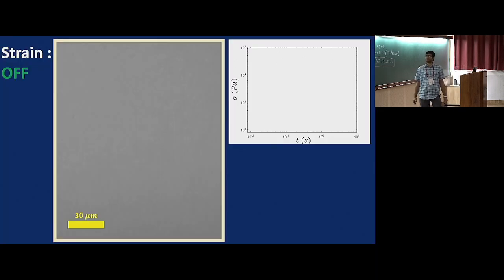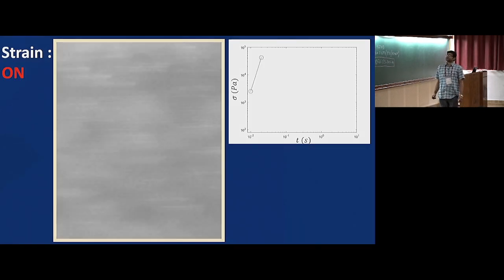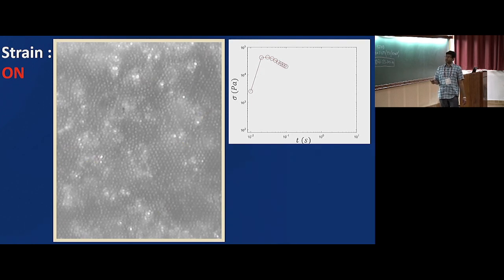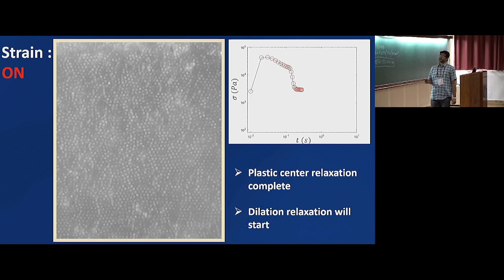The motivation behind this kind of imaging is that it is well known that for shear thickening or jammed systems under deformation, the particles pack, and then that pack competes with the liquid-air surface tension and the particles protrude out of the boundary, and one can image this. This is the typical boundary image we get under shear. Let me just play it. You see that all the particles protrude out.